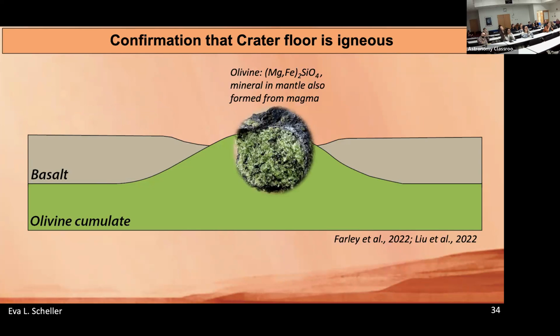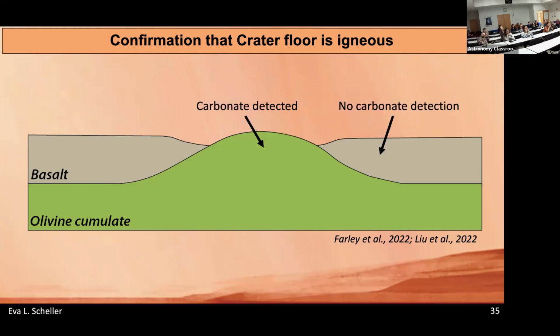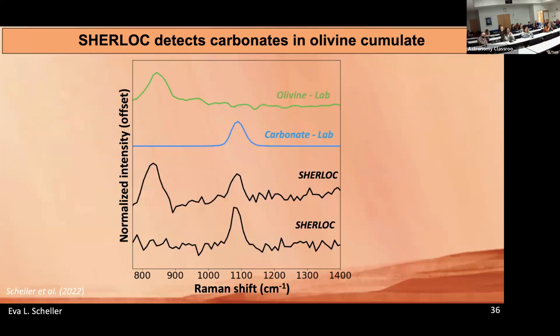rock in itself. And to summarize the different results before showing them, the key observation here was that we had carbonate detected in this olivine cumulate, but not in the basalt materials. And we'll talk about the implications of that. So here's the evidence for how we can detect this carbonate. I introduced these laboratory spectra before, and you can see here what the actual Sherlock spectra looks like on flight. Quite a bit more noisy. That's typically how it goes with flight data, but you can still see a nice matching Raman peak here, matching the carbonate, and a nice olivine peak here, matching the olivine.